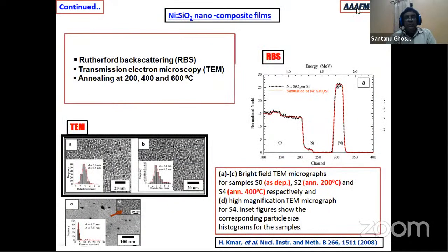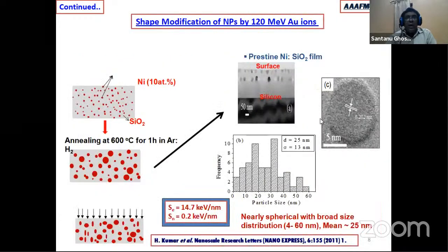After we grow the film, we do Rutherford backscattering spectrometry, and in this we get to see the different elements present in the sample. Here you can clearly see the presence of nickel, silicon, and oxygen. By fitting the spectra, we determine the thickness. We annealed the samples at 200, 400, and 600 degrees centigrade in order to grow the particle size, as evident in transmission electron micrographs. In a high resolution microscope, we can see the particles are more or less nearly spherical nanoparticles.